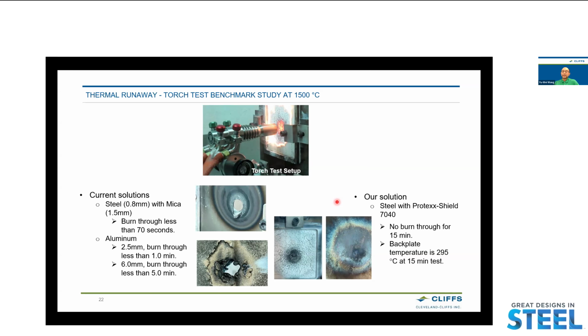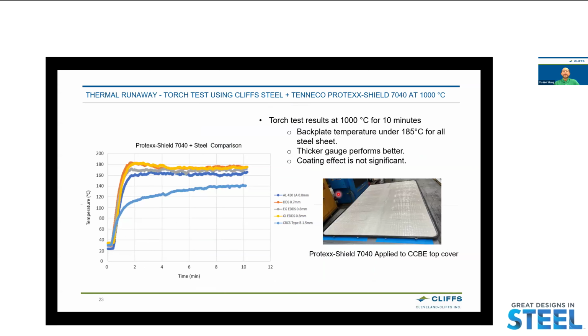And with the backplate temperature, it's less than 295 degrees centigrade at 15 minutes test. So it outperforms the current solutions as shown on the left. Yeah. And then this one shows the results of testing at 1000 degrees centigrade.